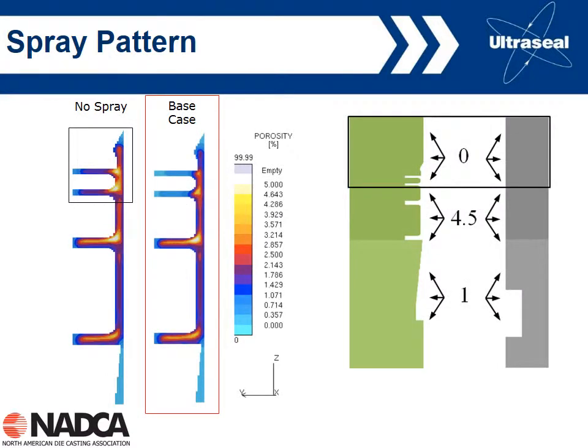We can look at it the other way around. What happens if we change the amount of spray on the top of the casting? So, for instance, if a nozzle is blocked at the top of the casting, we're spraying for 0 time, and so we're going to get more shrinkage porosity at the top of the die here. And so both of these are opposite to what we would like to do. As I said, what we'd really like is directional solidification from the extremity to the gate. So really what we want is to have the gate hotter and the extremity colder, and therefore we can get initial solidification at the extremity, flowing back to the gate, and that gives us longer time to feed shrinkage, and therefore we can do a better job of pushing more liquid into the mold.